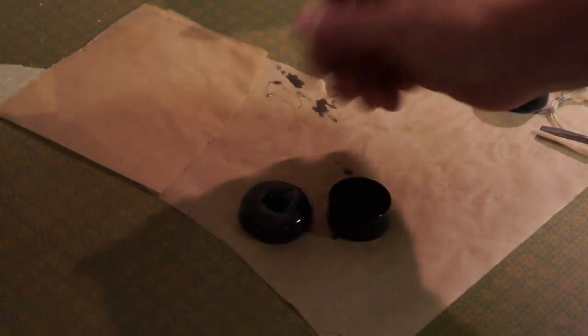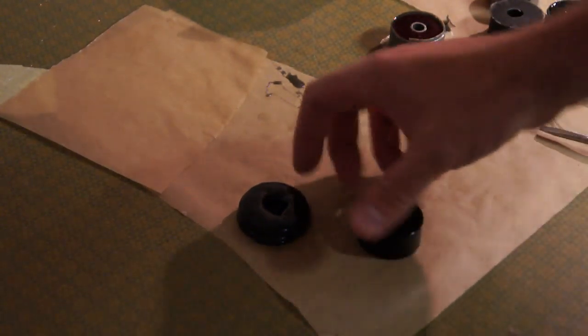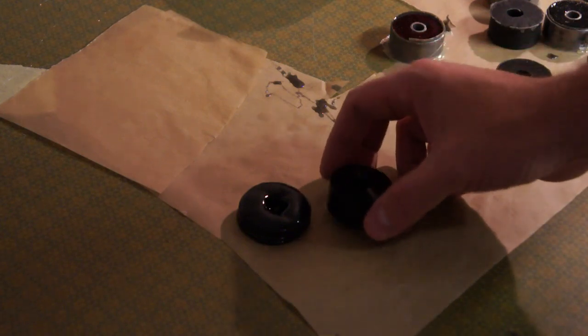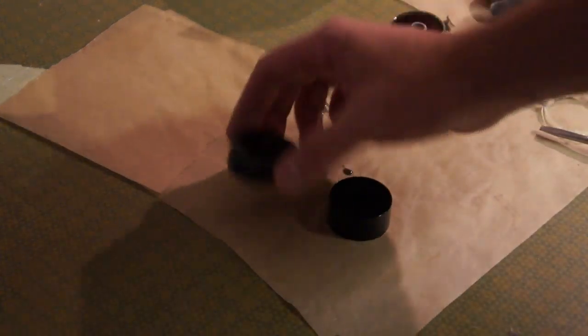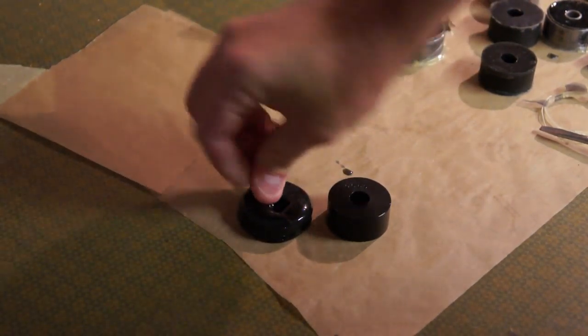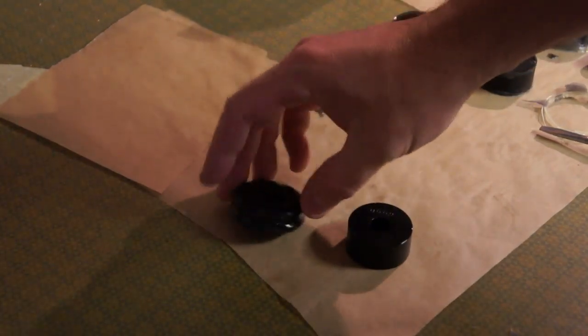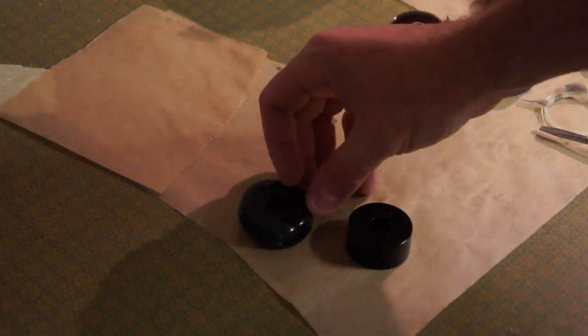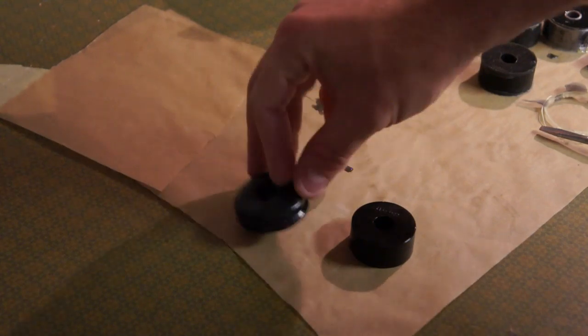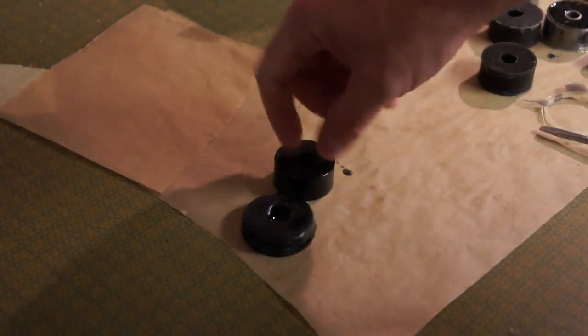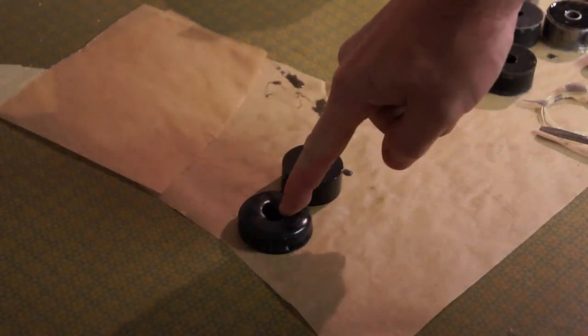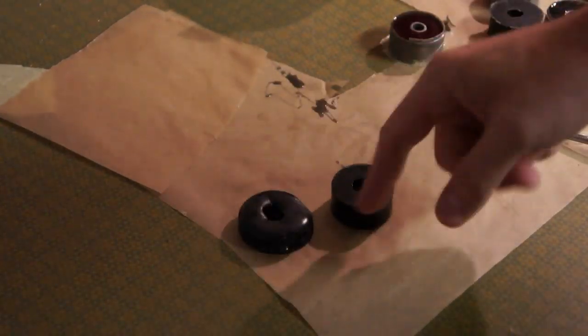So it turns out it is extremely important. I knew it was important, but it is extremely important that you get the mixture correctly. So I made two batches of eight tie bar bushes, and here is the first mixture. It's soft and it's still sticky, even after a couple days of letting it dry. This is no good, this is absolute garbage. This one I used too much of the additive and not enough of the base compound, and so I messed up the mixture and it doesn't set right. Here's the product I'm trying to mimic, an actual superflex tie bar bush. So you can see it's hard, it keeps its shape. This one just kind of oozes still, it's not getting firm and I can push down it and I can deform it easily and it doesn't bounce back to shape.